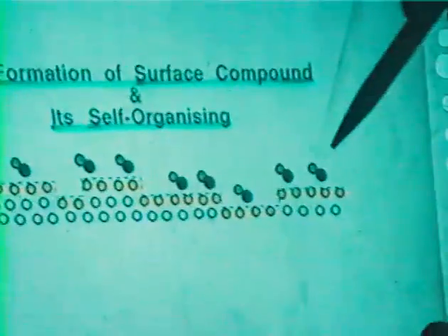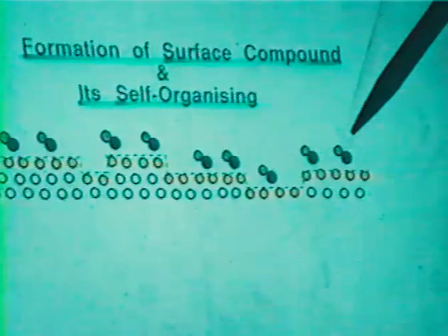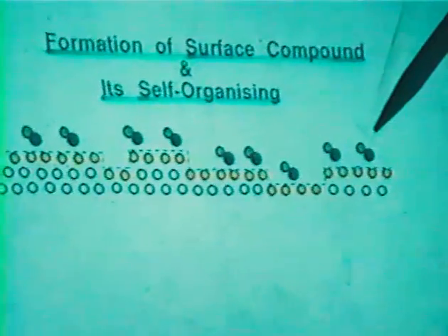So in this period, the surface is covered by a hydroxide overlayer, which is the intermediate for the water formation reaction. However, that stops the H2-D2 equilibration reaction perfectly. That is this case.